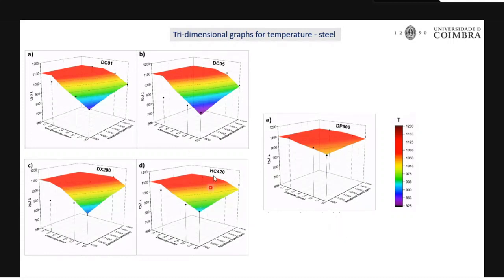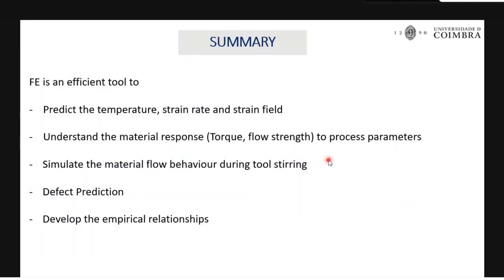Okay. So coming to here, you can see that for DC05 and DX200, we have some differences. In the case of DC05, maybe it is because of some error due to the emissivity during the temperature measurement, so we have a misfit here. And when it comes to DX200, we also have a misfit, and this can be related to the coating thickness, because DX200 is a galvanized steel. In galvanized steel, you will have a zinc coating over there, so this may disturb the contact conditions. So we got some misfit values in the DX200. Otherwise, the model is perfectly fitting with the experimental conditions.